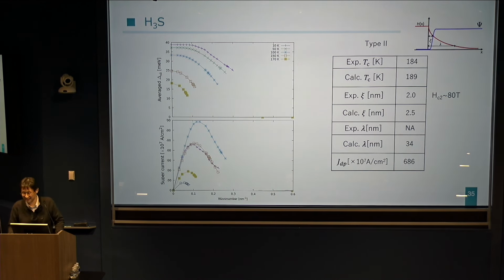And regarding the magnetic penetration depth, as far as I know, experimentally this quantity is not yet determined. But according to our calculation, it should be 30 or 40 nanometers. And interestingly, the number of JDP, the depairing current, is extremely large in this case.